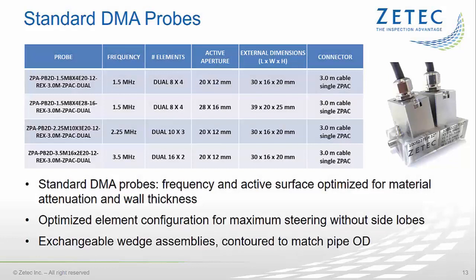Based on long-time experience and supported by acoustic beam simulation work, Zetec has designed a set of standard DMA probes. The frequency and the active surface of each probe are optimized for a given material attenuation and wall thickness range. Two probe heads are attached to a single Z-Pack connector to simplify field deployment. The element configuration in each design was selected for maximum steering capability without any relevant side lobes. We also offer exchangeable wedge assemblies with minimal footprint in the incidence plane and contoured to match the pipe OD. The wedges include carbide pins and irrigation points, and they are compatible with various Zetec and third-party scanners.